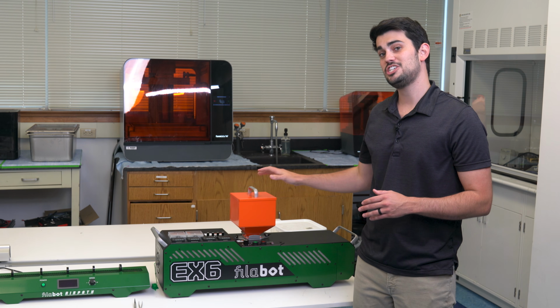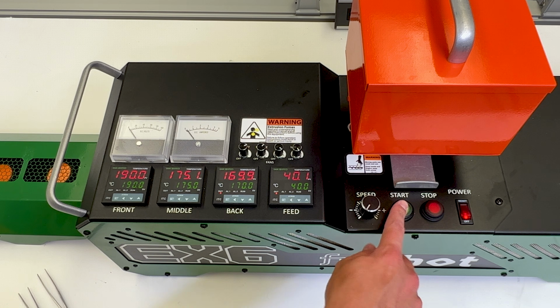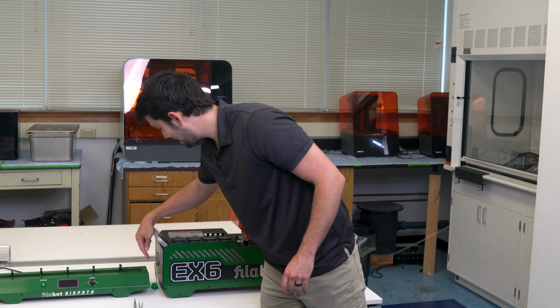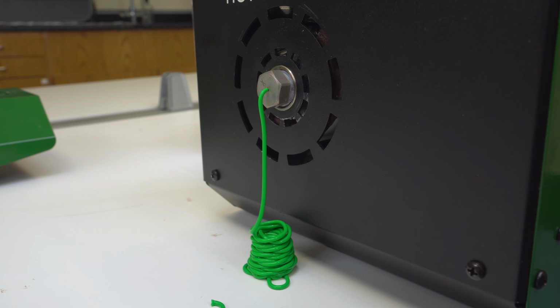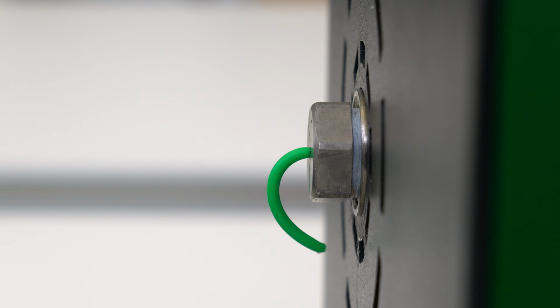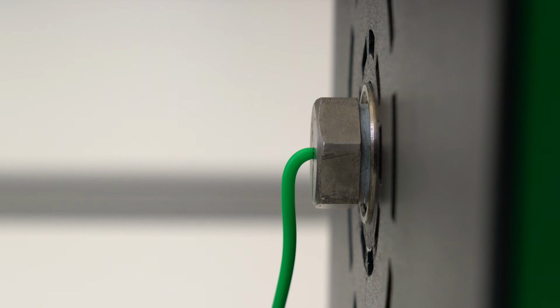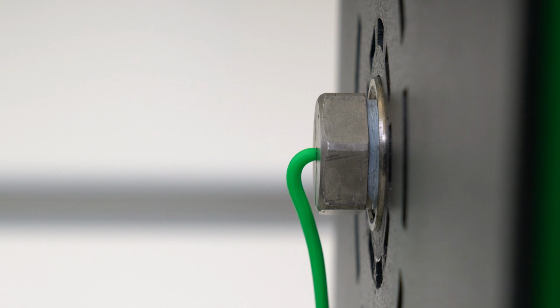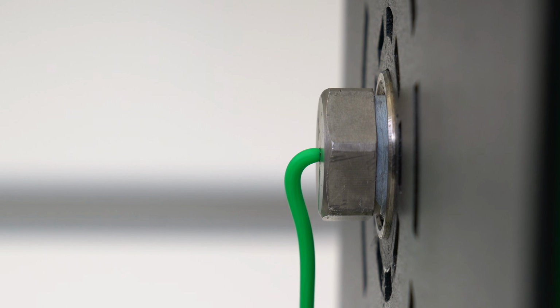The extruder has reached its set temperature. I went ahead and clicked start, and now you can see the plastic is pooling up down here. If you look closely, you can see the plastic melt has a slightly larger diameter than the orifice of the die. This is known as extrudate swell and is due to the elasticity of the molten plastic.